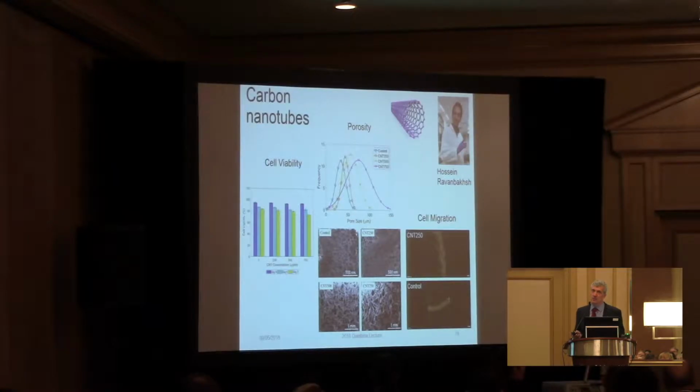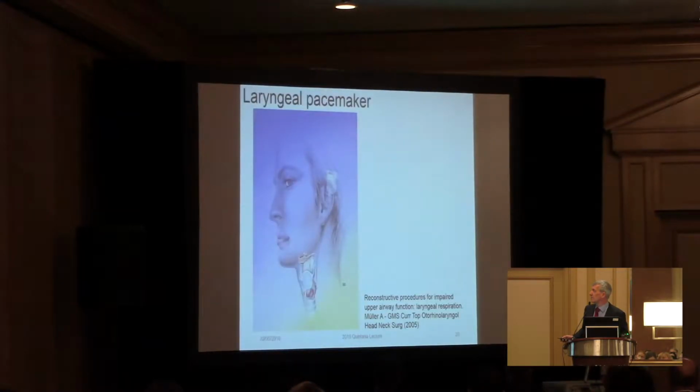So one of the things we do is we put cells with staining agents, and then we take long-term microscopy pictures to see whether or not the gel is able to recruit cells inside the biomaterials, and to see whether or not we have good migration of the cells, if they find adhesion points and they're able to move through the gels. This is important. Basically, you want the cells to be able to move, to be able to reproduce and to stay viable.